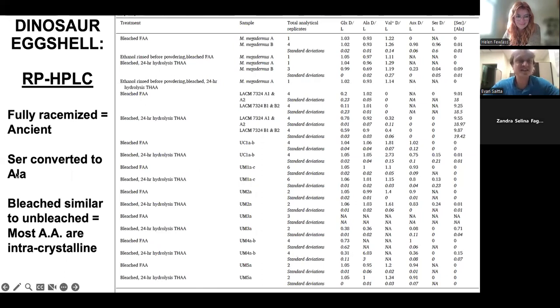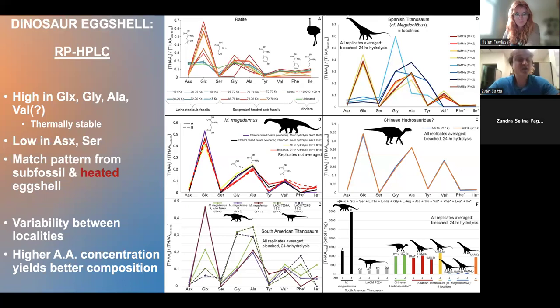What else? Serine to alanine is another indication that you're dealing with ancient material. The fact that you get similar results between bleached and unbleached could be consistent with most of the amino acids being within those crystals. The paper that we published has a probably too long section that I wrote going into every minute detail about this, so I would recommend looking at that if you want to be bored to death. But there's always uncertainty with it. Could these be contamination? Sure, but what I can tell you is they're definitely more promising than the results we got with the dinosaur bone.